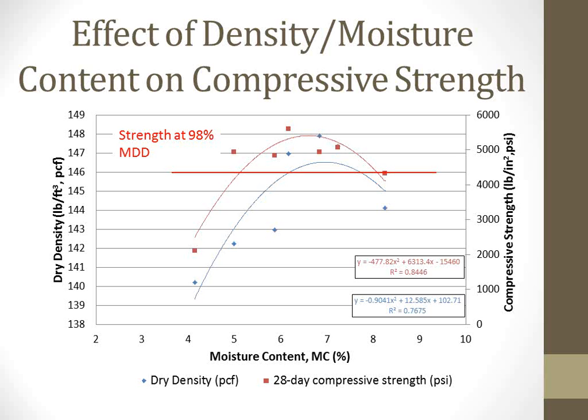So to look at the effect of the density and moisture on strength, I poured 2x4s out of Proctor samples and plotted here. That red line corresponds to 98% of the density, and the strength decreases about 1,500 psi from the maximum just by decreasing density by 2%. So it validates the minimum 98% that is typically specified in construction, and shows the large effect of moisture on the hardened properties.